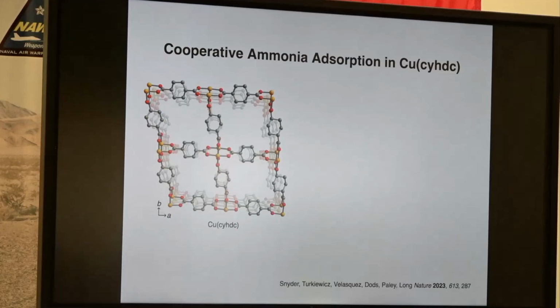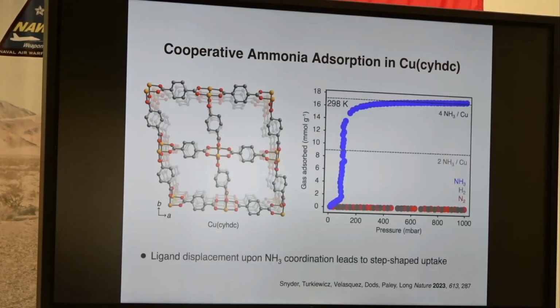Ammonia, we've recently shown we can do ammonia. The way to get selectivity is ammonia is a great ligand for metals, and it will displace things like carboxylate on copper. And so here's a very high capacity stepped uptake of ammonia into this material. And now with the Hill model, we get n equals 10.